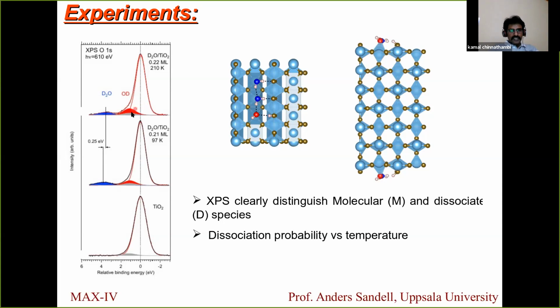So the most important thing is that using this XPS technique, the experimentalist is able to distinguish the peaks between the OD and the water molecules, so that XPS can be used to differentiate both the molecular and the dissociated molecules. They also perform the experiment at different temperatures. You can also see that when you go to different temperatures, there is a shift in the water molecule peak. So you can use this to get structural information from the experiment. That is one thing.